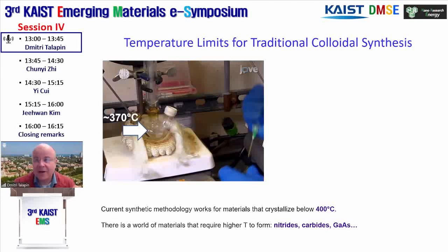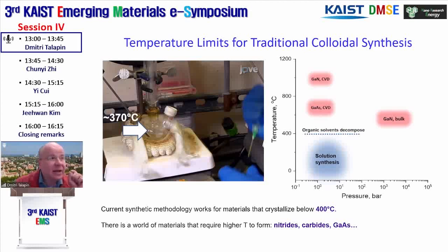At the same time, it's still not enough to meet the conditions that have been previously proven to be optimal for growing materials like gallium arsenide or gallium nitride. So if we look at the parameter space accessible for solution chemistry and compare it to parameters used for CVD growth of gallium arsenide or gallium nitride, we will find that we are pretty far away from where we want to be. In other words, the current synthetic methodology works really well for materials that crystallize below 400 degrees Celsius. But if we try to apply solution chemistry to grow, for example, gallium arsenide quantum dots, we are out of luck, and that has been proven by about 30 years of unsuccessful attempts to make these materials by solution chemistry.